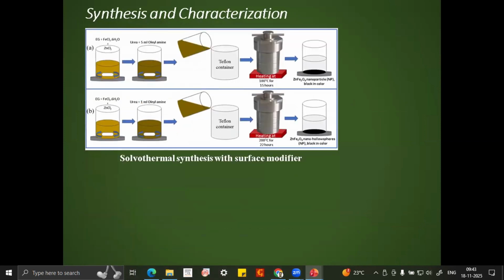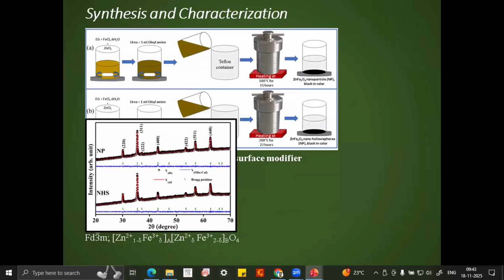This is the synthesis and characterization slide. We have synthesized our samples by solvothermal synthesis with oleylamine as the surface modifier. This is the XRD pattern with the Rietveld refinement analysis. The chemical formula shows that both the non-magnetic zinc and the magnetic iron are at the tetrahedral A site and at the octahedral B site. So both systems are synthesized in mixed spinel form.